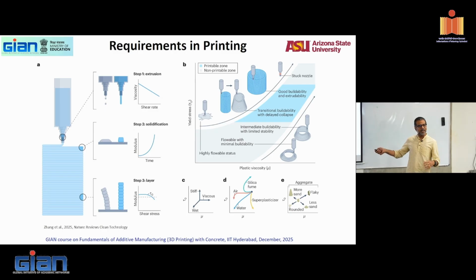And this tells you only half the story. Yield stress is not the only thing. You have other parameters also, which we will talk about. And then as you get to a higher place, this blue zone is actually a good zone. A certain yield stress with a certain viscosity will get you good enough buildability with delayed collapse, good enough buildability and extrudability. But if you further increase the yield stress, your material will get stuck in the nozzle. So this picture, try to keep it in your mind.